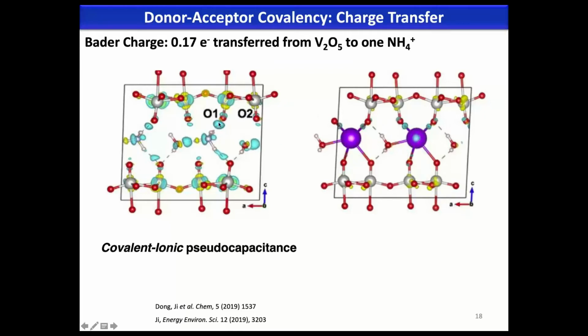You can see that in ammonium, the electron cloud distribution is more delocalized, sort of shared by ammonium and oxygen atoms. And there is 17% of charge transfer from the oxygen of V2O5 to ammonium plus. Essentially, the ammonium ion is not a 1+ charge carrier inside the lattice, it is 0.83 plus. So that is quite interesting. It means actually the ammonium ion itself can store energy, can store charges, right?